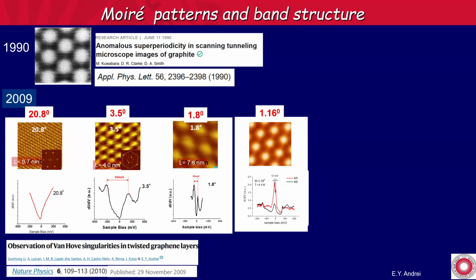Not only does it create pretty patterns, but actually it changes the band structure. And when you change the twist between the layers, you start out when the twist is larger than 10 degrees, you don't see anything. You see the V-shaped band structure. This is a density of states. This is an STM measurement that was done in our group on CVD graphene that was suspended on a transmission electron microscope grid, and then we walked the STM on top of it.